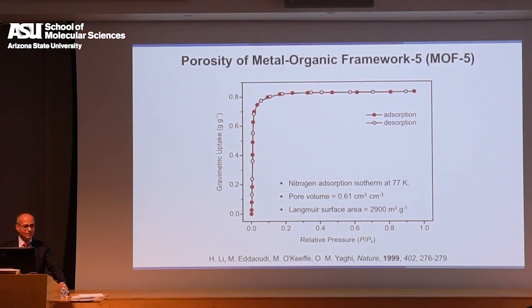And on top of that, I wasn't going to say to the world, I just broke the 1,000 year record held for porosity by carbon, without sending it to an independent company at the time in Georgia to confirm that the surface area was what we think it is. Actually, the numbers always hovered above 2,900 because in those days we didn't quite understand the chemistry of the pore. We can evacuate the pore, but we could never figure out if it is completely evacuated or not. It turns out that MOF5 now, we can activate so well that it has a surface area of almost 4,200 meters squared per gram.